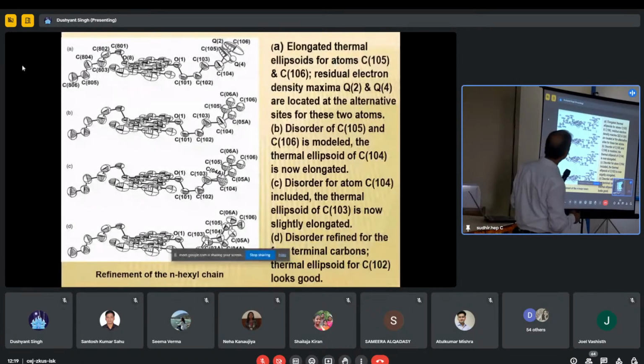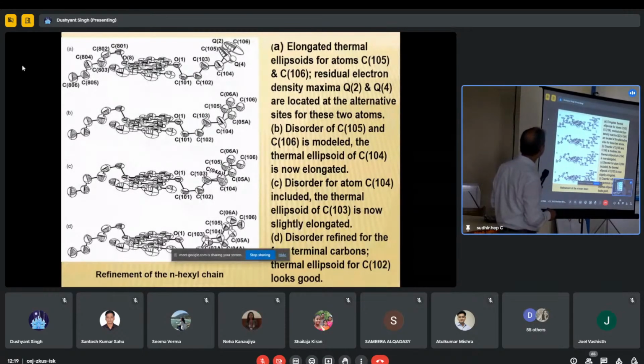Cigar shaped. Now when I resolved these 2 atoms in the molecule, C106 and C106A, C104 started showing an elongated shape. So this means that this is also disordered. Now I have resolved it.